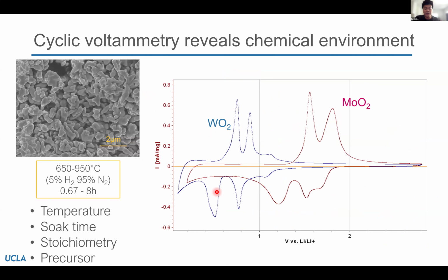And so, going ahead here, how we can infer that, we have some methods such as pair distribution function analysis and XAFS that support this, but here's a more visual way to look at that, talking about CV. So like Linnea mentioned in the last presentation, cyclic voltammetry, where we take an electrochemical system and we alter the voltage at a set rate, gives insight into redox reactions. So what I have plotted here in red is the CV of molybdenum dioxide, and in blue is of tungsten dioxide. And each of these sets of peaks corresponds to molybdenum 4+ and 3+ redox reactions, and the same for tungsten.